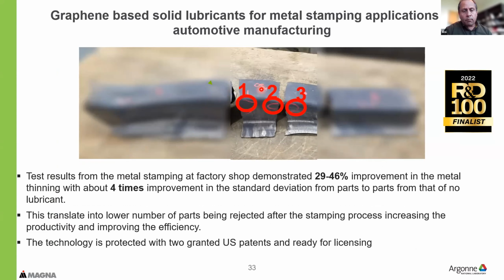Again, this is blurred intentionally, but what we have shown here is that there is a 29 to 46% improvement in the metal thinning process, about 4 times improvement in the standard deviation that leads to a lower number of parts being rejected. So that means increasing the productivity and improving the efficiency. This already has 2 granted patents and got the R&D 100 finalist award. But it was really interesting to see the journey of this technology right from simulation, lab testing to the actual shop floor and giant system where this happens, and see that it is working nicely, and how nanomaterials are making such a big change in the automotive industry.